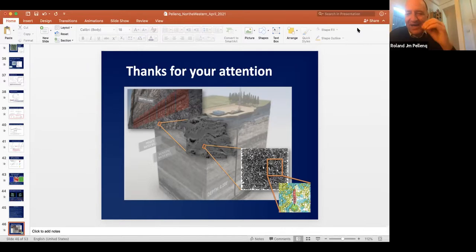But the thing is that with the current technology, the amount of those nanopores is very large. This is a very key feature of the texture of those porous carbons. And the message to the industry was that you're leaving behind the treasure of this shale gas exploitation by not assessing the amount of nanopores where at least methane molecules are sitting. So now the goal is to make them move. The first step, to be recovered, is to diffuse through this network of nanopores.